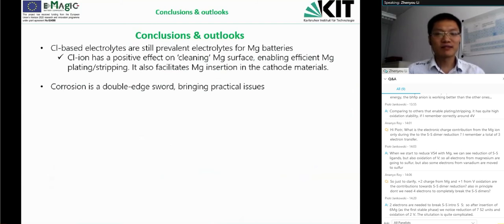The fact is that chlorine has multiple functions in the magnesium system, enabling magnesium plating and also insertion and de-insertion. It's still difficult to find, or there's no report about, additives that can replace the chlorine ions. But we should also realize that the corrosion issue is really a big problem, especially if we want to scale up the system. In manufacturing, for example, this will bring a lot of problems and needs more effort.